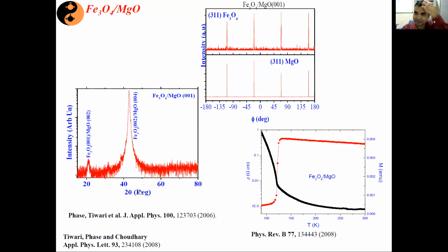And how do I confirm that this is epitaxial? To confirm that epitaxial nature, we do an in-plane phi scan measurement, where you rotate your film in the in-plane direction by 360 degrees, record some other Bragg reflection, and probe how many times that Bragg reflection is satisfied in that 360 degree rotation. So you can see that it is satisfied 4 times, separated by 90 degrees. That means my film has 4-fold symmetry, which means it is spinel cubic in nature. And since these peaks match with those of the MgO substrate, the film retains the same crystalline arrangement as the substrate. That is why I call these films epitaxially grown on the MgO substrate.